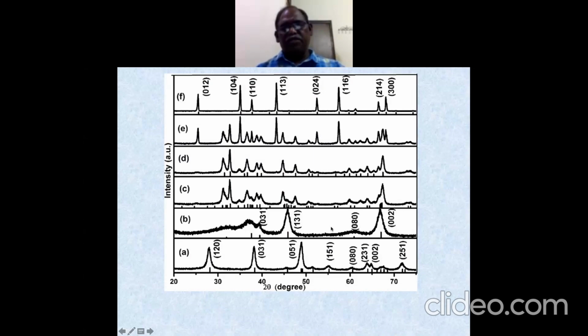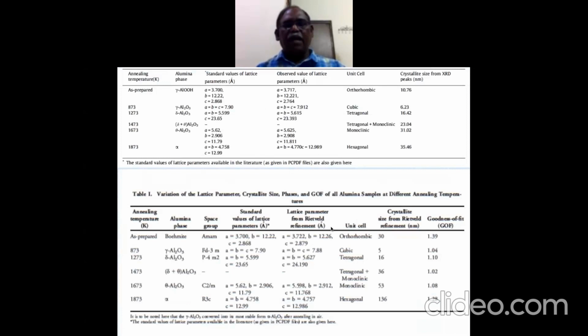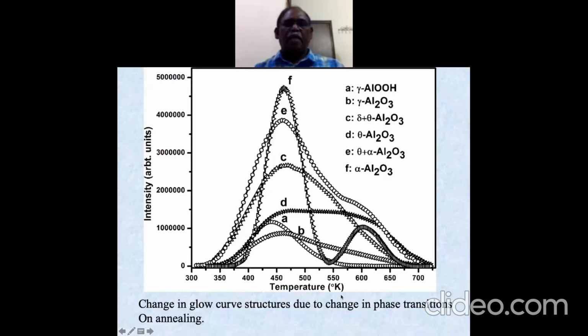So the lattice parameters will also be changed. So you have some hexagonal, tetragonal, monoclinic, cubic, orthorhombic, and all sorts of phases. And these are the different kinds of phases, and we wanted to see what its effect is on the local structure, and other luminescence properties we have also seen. But specifically, for the sake of limited time, I have shown only this. So there is a lot of change in its luminescence properties.